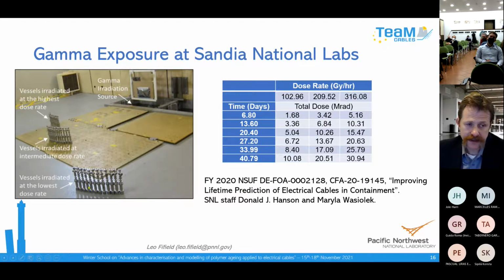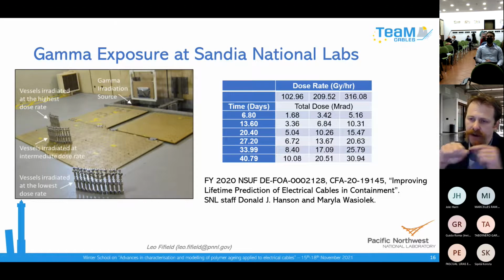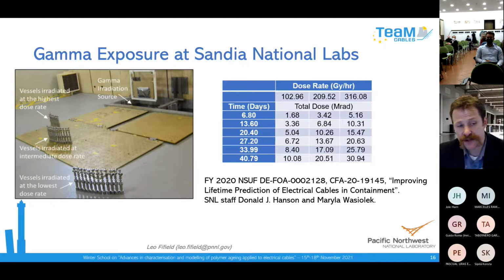In this example, these are loaded vessels with the polymer insulation samples. These were insulations we call straws, in which the metal conductor was removed so that we could perform tensile measurements on them afterwards. These straws were loaded in these vessels. They were sent to Sandia National Laboratory, another DOE laboratory in the southwestern part of the country, for gamma exposure. In this case, it's just at room temperature. They're exposed to gamma radiation at a series of 3 different dose rates. And there are many vessels here because they were removed over time, so we have a series of different doses at different dose rates.